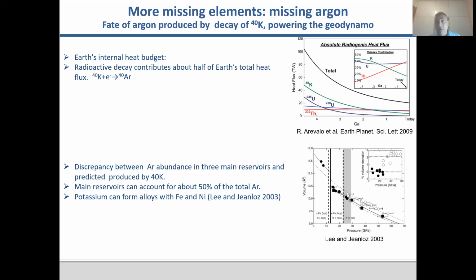Now, it is known from previous studies back in 2003 or before, for the case of nickel, and I will present some results, that potassium has no problem forming compounds with iron and nickel. I will give some more details in the next slides. Even at 10 GPa, one can form compounds between potassium and iron. So it makes sense that potassium may exist in the Earth's core, and then through the radioactive decay, you have argon.